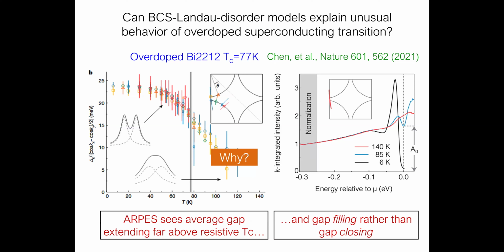So yes, in fact, I'll come back to it now. When I presented these results at some point, people from the ARPES community said, well, okay, you've got disorder and perhaps some inhomogeneity that arises from disorder, but can you explain the fact that in these overdoped BISCO samples, the gaps that one observes go considerably higher than the resistive TC, maybe as much as 30% higher?